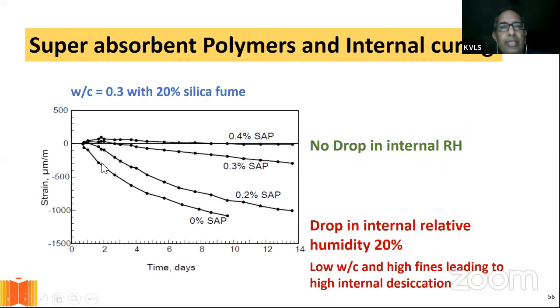And I just want to show you here that if I don't use superabsorbent polymers, this lowermost line shows the amount of shrinkage strain, the volumetric contraction, the shrinkage of concrete that's happening. If I add about 0.4% of superabsorbent polymer, I can basically reduce the strain down to zero. That means the shrinkage has essentially been cut down to zero.